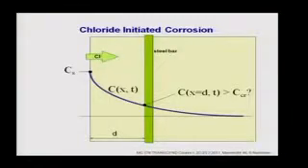The other mechanism that can initiate corrosion is chloride ingress — also a transport process, and much more complicated and not so well understood even today. You have a concrete surface exposed to a chloride environment from the sea or de-icing salts, penetrating in a completely different way into the steel, eventually reaching a threshold level at which reinforcement corrosion is initiated. Now it's ions that move — and ions can't fly, so they must move in water. You have to have a wet pore system, and with wetting and drying you can move ions with the water as convection.